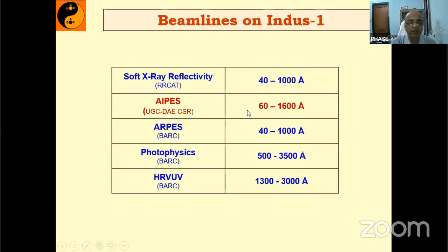So the energy range is again 60 angstrom to 1600 angstrom. Another beam line, the third beam line, is basically angle resolved photoemission spectroscopy. That one is by the BARC, and then the normal photophysics absorption beam line, also by BARC, is from 500 angstrom to 3500 angstrom. And then high resolution vacuum ultraviolet absorption spectroscopy, again 1300 angstrom to 3000. So these are basically the five beam lines available.